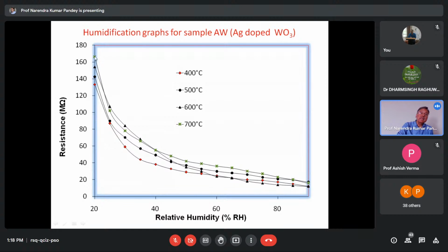You can see from here that initially the fall in resistance in the range up to 50% relative humidity is very good for this material. After that, the fall is slow. That means it is highly sensitive in this region, and it has lower sensitivity in the higher region, for this particular material, Ag doped WO3.